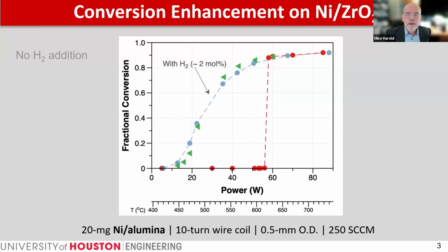Now, that may not be a surprise, but what is notable is that with the addition of hydrogen, the lower steady state is completely removed. So this red lower steady state with the ignition obtained without hydrogen addition is no longer present. And so in an experiment starting at low power and proceeding to high power, we follow basically this high branch that would only exist at lower power when hydrogen is not added. But with hydrogen added, we follow this trajectory.